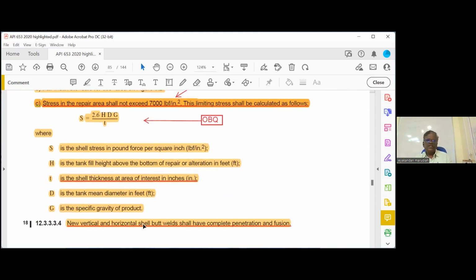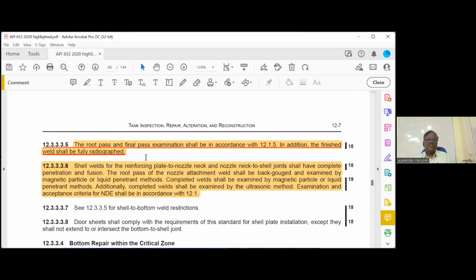The new vertical and horizontal shell should have complete penetration and fusion. Then the root pass and the final pass, according to the code, shall be radiographed. So for all repairs, you have to go for full radiograph. If you are going for exemption, we call it a golden joint.